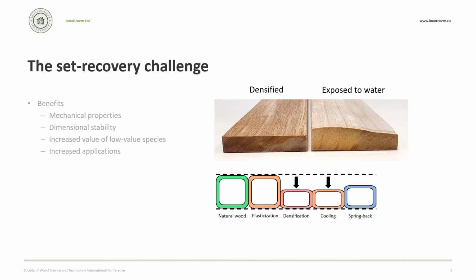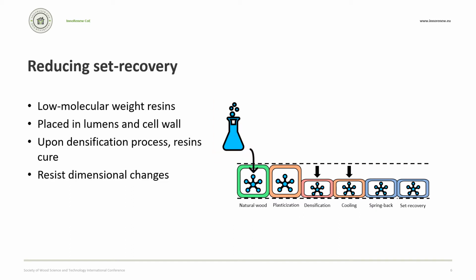However, if the treated wood is exposed to moisture, it can partially or even completely return to its original state. This is referred to as the set recovery. One method used to try and reduce the set recovery response is by using a resin inside the wood to physically hold the wood in place from swelling. This is achieved by impregnating the resin into the wood, which when compressed and heated during the densification process polymerizes.